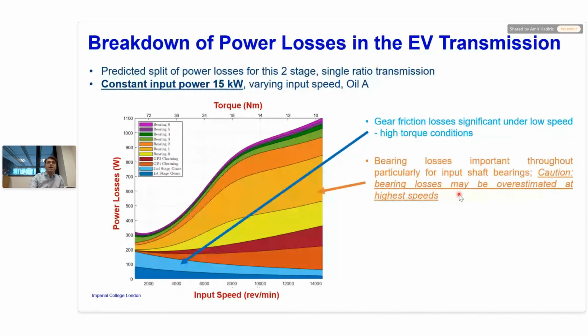As you increase the speed, the bearing losses become the dominant. Overall, they are by far the most dominant. So bearings contribute by far the most, apart from our low speeds. The churning losses, again, almost nothing at low speeds, and then significantly higher at high speeds.